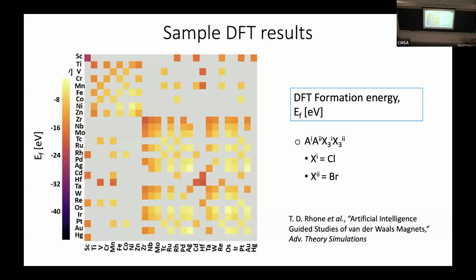And again, we have A1 substitutions on the horizontal axis, A2 substitutions on the vertical axis, and each square is a different material. And again, there's missing data here. And in this panel, they're now both mixed X sites. There's both chlorine and bromine here. This is a so-called Janus transition metal halide.